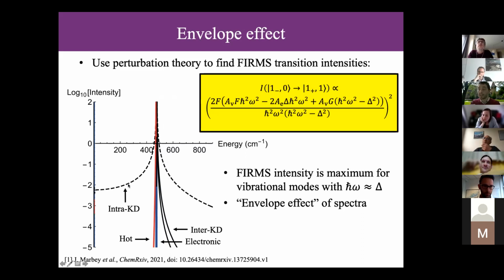But this is where you're making a simultaneous vibrational and electronic excitation. So we're going from, let's say, the lower part of KD1 and no vibrations up to the upper part of KD1 and 1 vibration. So we're changing electronic and vibrational quantum, and the intensity of that transition is driven by a photon with energy h nu, which equals delta E plus h bar omega, right? So the energy of the vibration does not equal the energy of the electronic transition you are doing. It can be the electronic transition of anything, any other gap in your Hamiltonian. As long as there's a resonance, you get this kind of pattern.